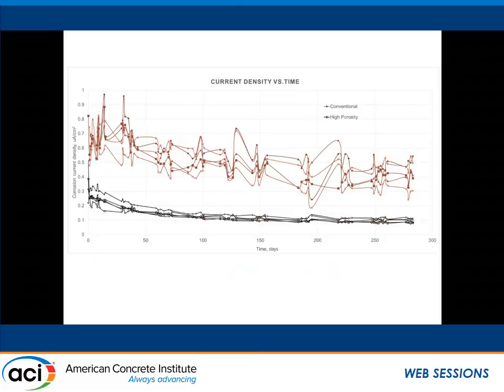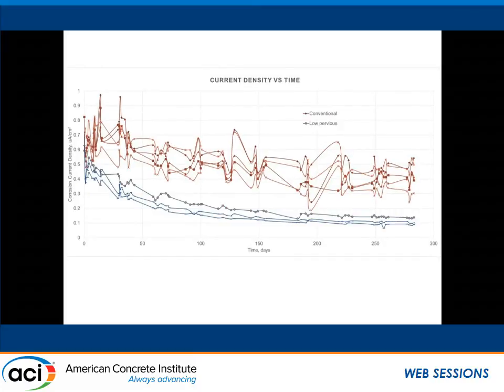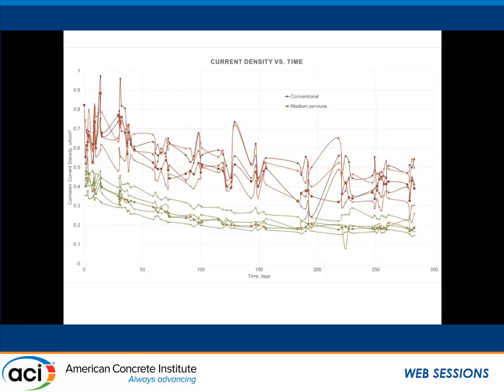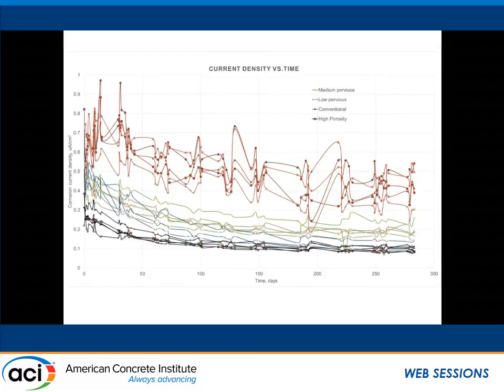But typically what happens is initially you get a spike in current because your steel is passivating. And then once you get that passive coating, it kind of drops down. And then once corrosion initiates, this is going to spike up. We say if it's above 1 microamp, then we have corrosion happening. So here's our high porosity pervious, really low. Here's our conventional. Low porosity pervious, a little bit higher, but still low. And here's our medium pervious, still low. If we look at those, we haven't initiated corrosion in any of these samples, but we do see that the pervious system has a much lower potential at this point.